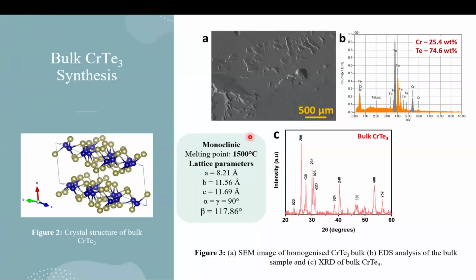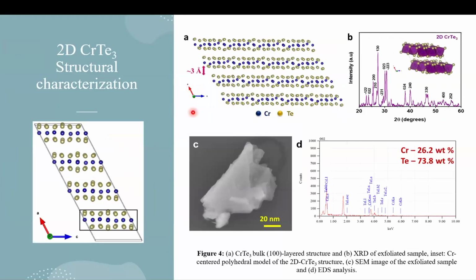So the bulk chromium telluride was synthesized by induction melting, and we confirm its phase formation using SEM, EDS, and XRD. It has a monoclinic structure with van der Waals bond in between layers, and it was easier to exfoliate them. We did exfoliation in a liquid medium, IPA, and we were able to obtain overlapping thin layers. These layers are not exactly as what you get during chemical vapor deposition, but they fall in the two-dimensional limit, and we can use these thin structures for device fabrication.